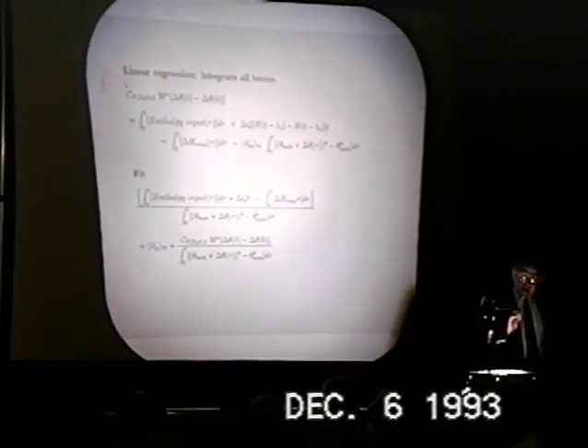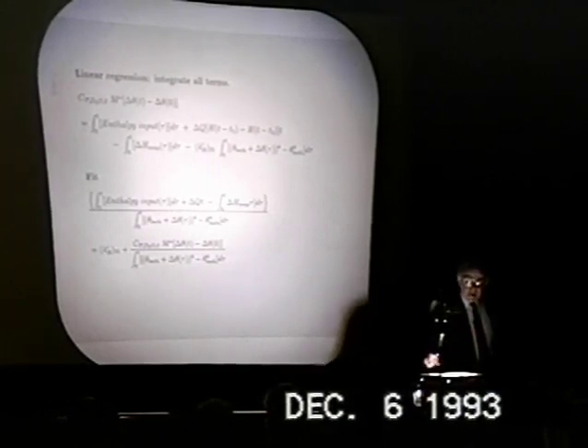We do this in two steps. First of all, we look for the heat transfer coefficient on the assumption that there is no excess enthalpy in the system, and then we can use a modified approach, saying there is excess enthalpy in the system. So if we say there is no excess enthalpy in the system, and calibrate the system, we get a value of the heat transfer coefficient based on the assumption that there is no excess enthalpy generation in the system. However, we can use the calibration pulse and repeat the process and include the excess enthalpy, the calibration pulse, in the equation, and then we get the actual heat transfer coefficient, which takes account of the possibility that there is excess enthalpy generation in the system.